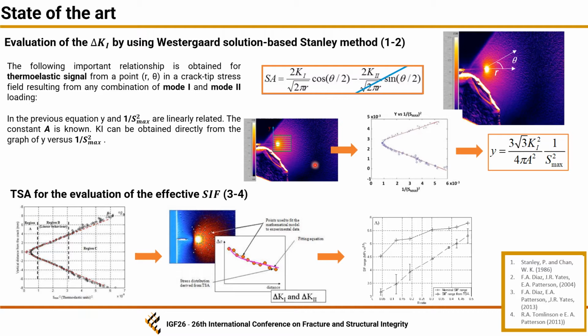On the other side, instead of using a linear interpolation method, the over-deterministic least squares fitting method can be used for a more accurate estimation of the stress intensity factor. In this case, by using a Williams series expansion. In this work, the approach has been used for assessing the effective stress intensity factor from the thermoelastic map.